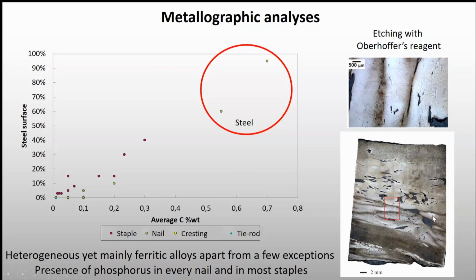The bright zones are higher in phosphorus than the dark ones, at the mesoscopic scale, but also at the microscopic scale. You can see differences here with what we call the ghost structures, which show microscopic high variations in phosphorus content. So phosphorus tends to embrittle the iron, but also to harden it, like steel. So this ferrite iron is actually sometimes as hard as the steel ones.